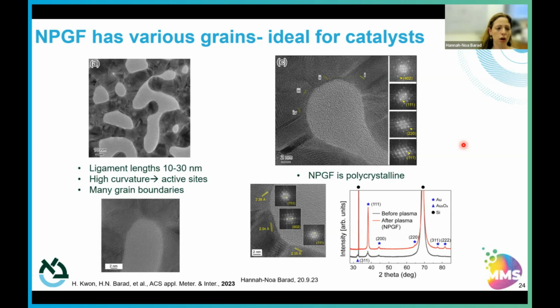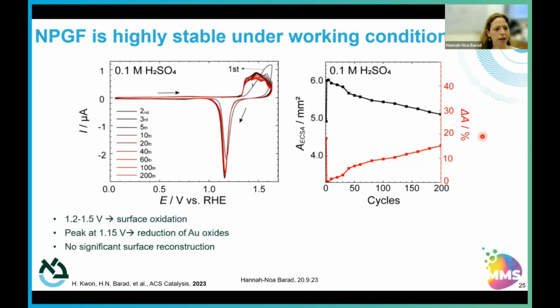And we looked into the stability under electrochemical working conditions, which is, of course, critical because electrocatalysis is done, of course, under bias. So first, we started out with looking at acidic media. And you can see from our first cycle to the second cycle, there's only one reconstruction, first to second. And then the rest of the time, the surface pretty much remains the same over the scans. So this is actually very significant because we don't get a lot of surface reconstruction, which means that we have high stability over time. And if we look at the surface area evolution over time, we only get a reduction of 15% in the electrochemical surface area, which is really nice given the high porosity of these materials.